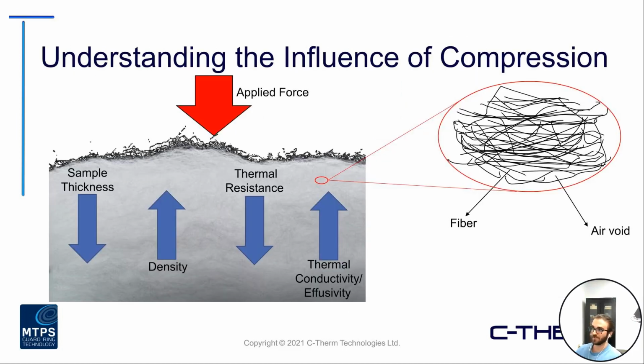Up next, taking a look at the influence of compression. So certain materials may be more compressible than others, but as a general rule, if you're applying any amount of force on the top side of a sample, this is going to result in a decrease to the thickness, resulting in an increase in density. This leads to a net decrease in thermal resistance,